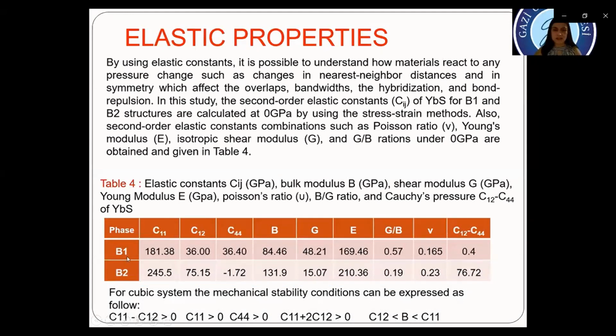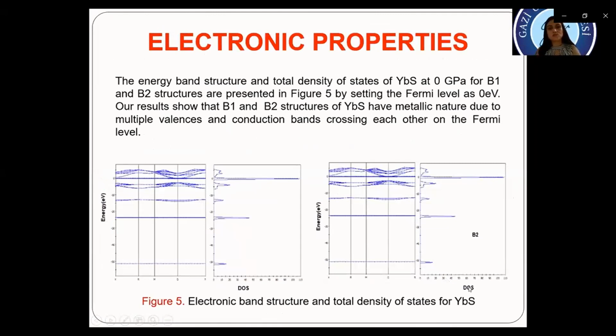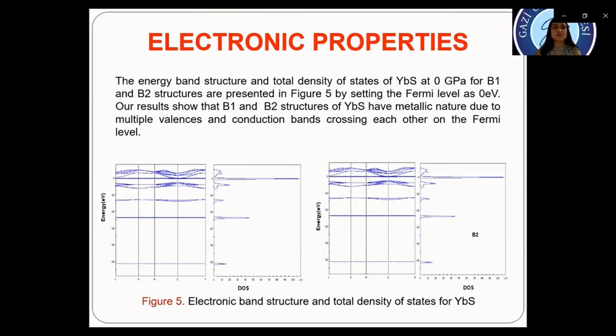The B1 phase is mechanically stable, but B2 is not mechanically stable. Electronic properties. The energy band structure and total density of states of ytterbium sulfide at 0 gigapascal for B1 and B2 structures are presented in figure 5 by setting the Fermi level at 0 electron volts. Our results show that B1 and B2 structures of ytterbium sulfide have metallic nature, due to valence and conduction bands crossing each other at the Fermi level.